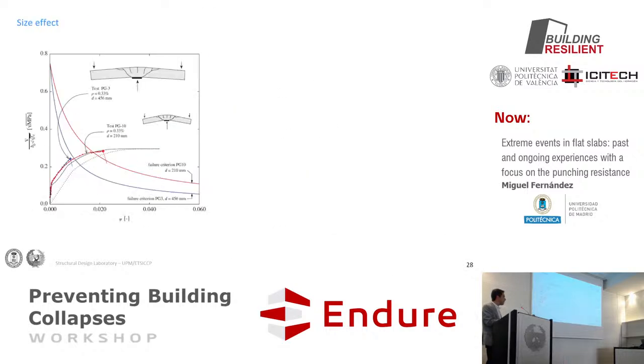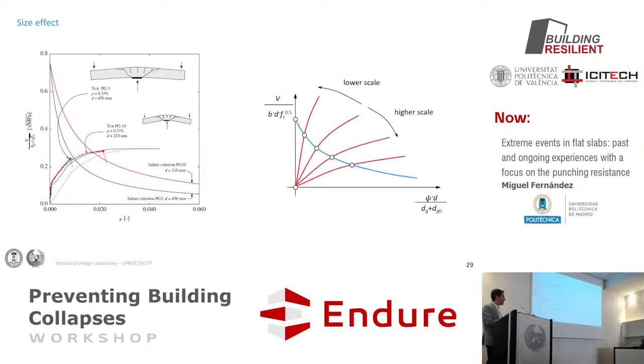This is something you can calculate consistently. This is what you see in tests, actually. Members of larger size have lower strength, lower resistance. And this is what you get also in the theory. So if now we normalize the rotation by the size of the member, then for higher scales you are moving in this direction, so you're getting lower resistance. For lower scales, you are moving in this direction, so you are moving up. And you will eventually find that there is a limit to what you can get.